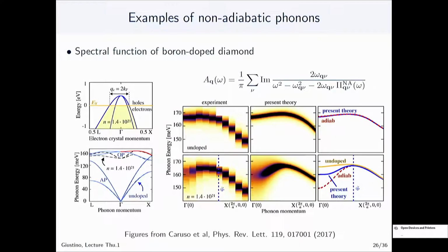So the other thing that you may want to consider, to answer a bit more broadly: here there is very good agreement with experiment, but we are really talking about smaller energies. If you look at the complete dispersions, generally the dispersions of the system are okay. If you want to do measurements which really target specific vibrational modes and you want to be accurate, then you need to include these effects. But if you're calculating phonons to study heat capacity, or properties which depend on an average of the phonon density of states, that should not be affected too much. So that's why most of the things that have been done so far work quite well, actually.